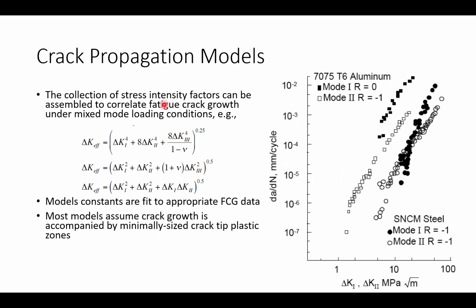How do we get these effective stress intensity factors? These factors are empirical in nature — we conduct many experiments and then do curve fitting or apply logic to derive equations describing the relationships under that loading state. Some examples include K-effective incorporating K1, K2, and K3 (the three loading modes), another including Poisson's ratio, and a simpler version with just K1 and K2. People produce their own versions, and some even use machine learning to develop these equations based on their data.